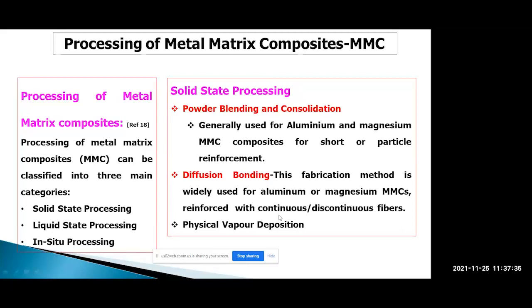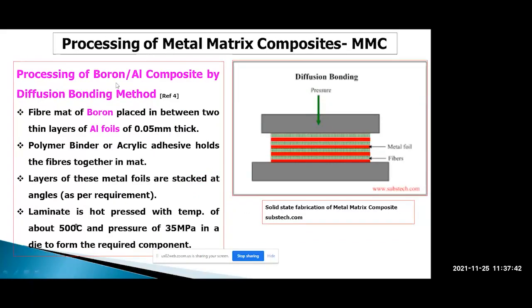Physical vapor deposition can also be used. Powder blending consolidation is for short fibers, and diffusion bonding is for continuous fibers. So this is boron aluminum composite made by the diffusion bonding method. Aluminum foils are placed between boron mats. The fibers are generally bonded in a mat with acrylic adhesive, and layers of these fine foils are stacked with the mat in between. This laminate is pressed under heat at 500 degrees centigrade and 35 MPa pressure, that is 350 bar, in a die. The dies generally used are graphite dies.